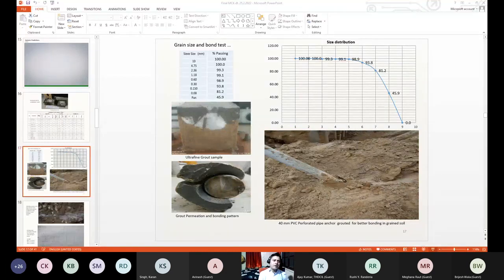Now I will go on to Shotcrete. The first time a spray concrete job was done was in the United States by the Cement Gun Company in Allentown as early as 1907, with the spray concrete product type gunite using a simple to operate compressed air driven pump. Similar to that figure, spray concrete mortar is a mixture of cement, silica, fiber, aggregate, additive and water, pneumatically projected at high velocity onto the surface and compacted by its own momentum. With respect to specification, certain criteria should be fulfilled, which shall be covered in this topic.